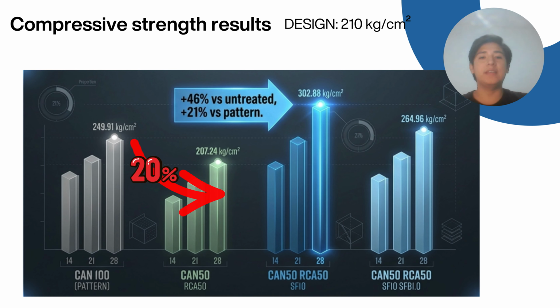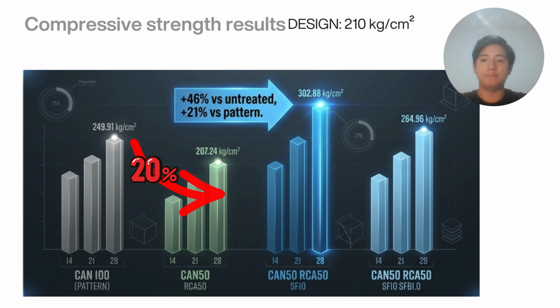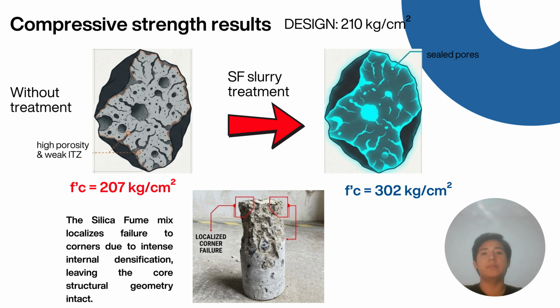As expected, replacing natural aggregate with untreated RCA reduced compressive strength by approximately 20% compared with conventional concrete. However, after applying the silica fume slurry treatment, the results improved significantly. At 28 days, the treated RCA mixture achieved an average compressive strength of 302 kilograms per square centimeter. This represents a 21% increase compared with conventional concrete and a 46% increase compared with the untreated RCA mixture.